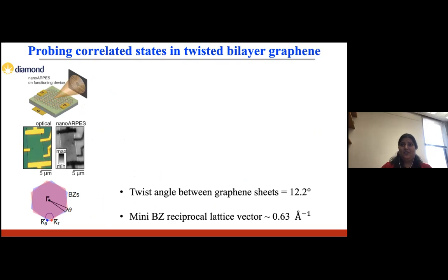To investigate the effect of gating on the energy and momentum dependent correlations of interlayer hybridization between these Dirac cones of the twisted layers, we fabricated twisted bilayer graphene devices where the twist angle was about 12 degrees. This corresponds to a Brillouin zone reciprocal lattice vector of about 0.63 inverse Angstrom. The important thing I want to point out here is that this is about 11 times larger than the mini Brillouin zone that you would get for magic angle graphene.